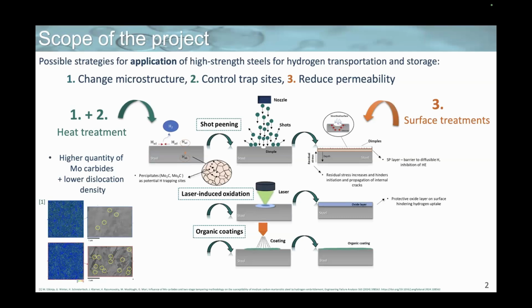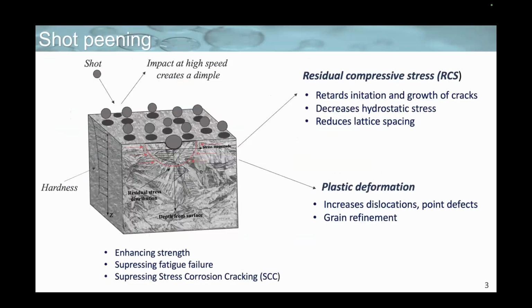The first two points, changing the microstructure of the steel and controlling the trapping sites, have already been successfully performed, and we managed to achieve higher resistance of the martensitic steels to hydrogen embrittlement by increasing the quantity of molybdenum carbides and lowering the dislocation density. To reduce the permeability of hydrogen into the steel, we are implementing different surface treatments. Three surface treatments, which are the main focus in this research, are shot peening, about which I will talk today, the laser-induced oxidation, and application of organic coatings.